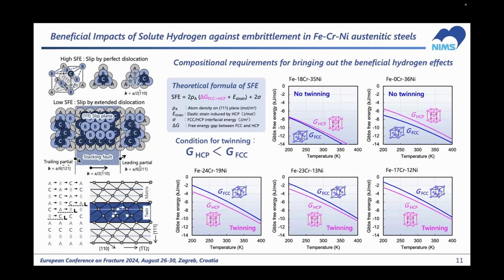So here I showed the thermodynamic calculation by using some CALPHAD software in the present five alloys. We found that in the alloys which show deformation twinning, the free energy of the HCP crystal structure was always lower than that of FCC. But in other alloys which didn't show deformation twinning, the energetic relationship was just opposite. So if we design the alloy so that we can obtain an energetic relationship like this, I think we can expect the same effect even in other alloys with different chemical compositions, and of course, under the suppression of martensitic transformations.